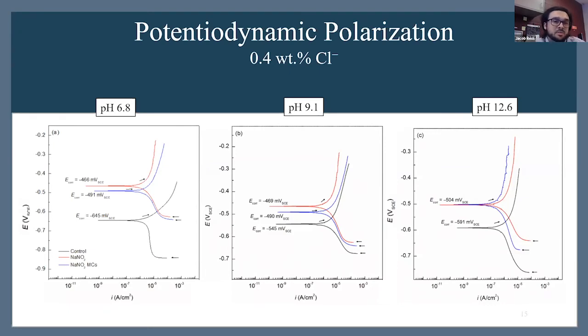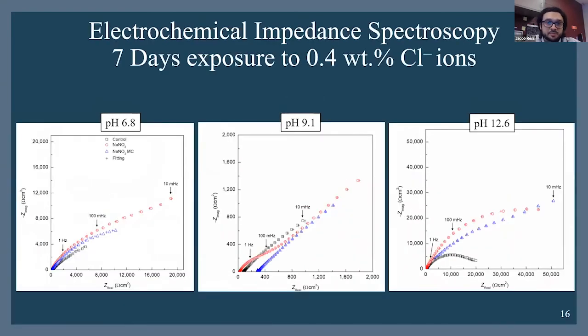And we see that the microcapsules, although showing a more active E-corr in the near neutral and pH 9 solutions, do show similar corrosion current densities and values to our free inhibitor solution. And lastly, in our alkaline solution, our simulated concrete pore solution, we see the most ennoblement by the microcapsules, showing comparable E-corr values to our free inhibitors, as well as lower I-corr and lower current densities in general. And by EIS as well, to corroborate our DC method.